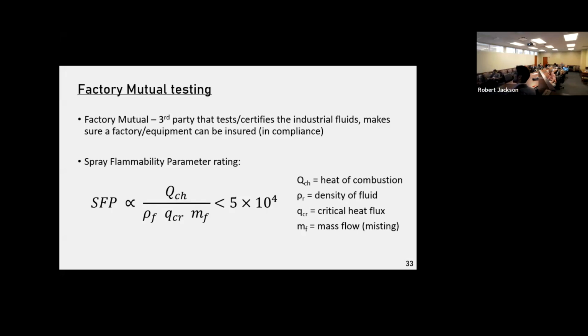The four parameters they test for are heat of combustion, the density, the critical heat flux, which is essentially the transition between liquid to gas. So does it evaporate faster than it vaporizes, kind of. And mass flow, so misting capability. And then they generate this SFP number. If you're above 5 times 10 to the 4th, you fail. If you're below 5 times 10 to the 4th, you pass.